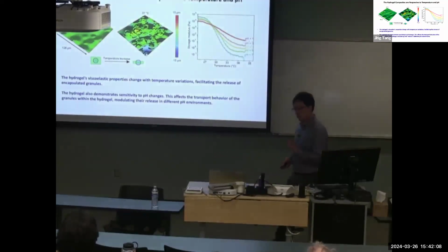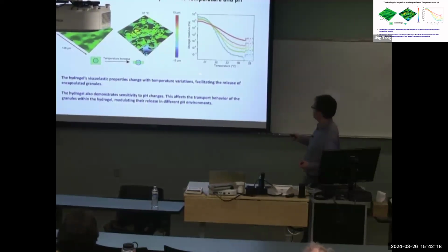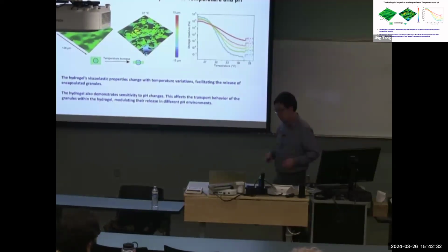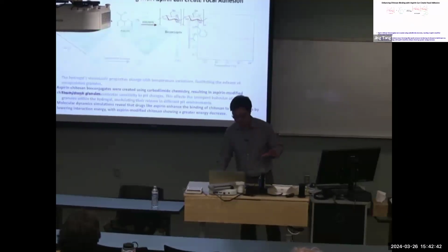You can also do rheology analysis to understand how the granules are going to get released, either by temperature increase or by pH variation. So the idea here is to look at the viscoelasticity properties, and specifically, for example, the storage modulus. If your storage modulus goes down, and you see the viscoelastic property become more viscous, then the granular particle can release better. Otherwise, it will just be embedded in the matrix and will never come out. You want them to come out in order to attach to the tissue surface and form a focal adhesion.